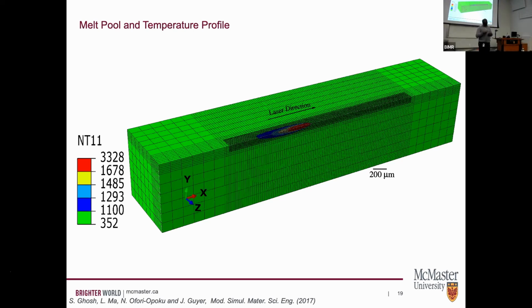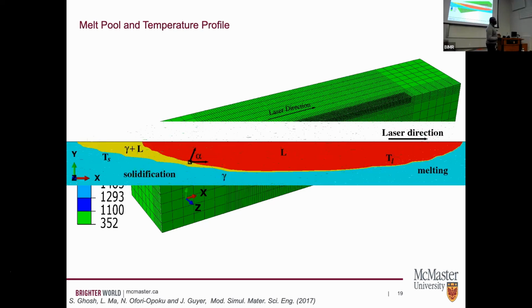And what gets put in is things like what's the density of the material you're interested in, what the scanning velocity of the laser or electron beam is like, and what the power of that energy source is. So when we do, we could get a temperature profile that kind of looks like this. After the laser rasters, it melts a certain area. So you have a liquid, you have some two-phase region, and then you have the solid substrate that it's on. And so we take this information and then we input it into a phase field description.